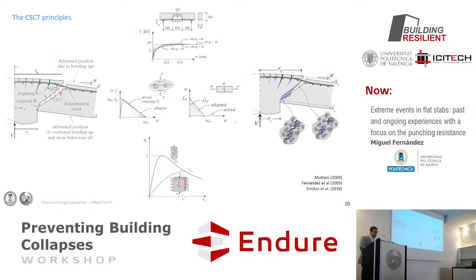So now, once we know that, we can integrate and calculate the amount of resistance. So we have here, as I was saying, a kinematical model. It's one crack that is characterized by a shape, which is again like a parabola, and also with this point of distance, well, just a geometrical characterization. And then it has a rotation, which is giving this blue component of opening, and then a penetration. And by having this, you can go to constitutive laws.